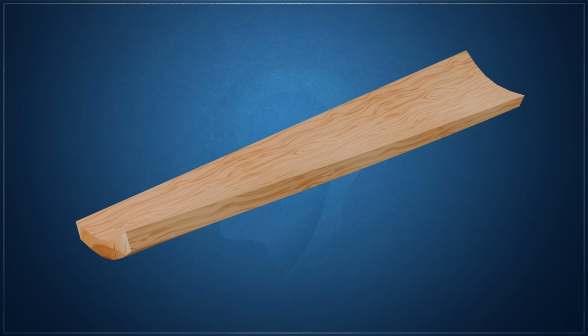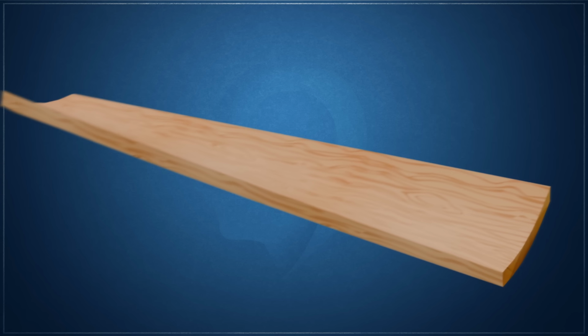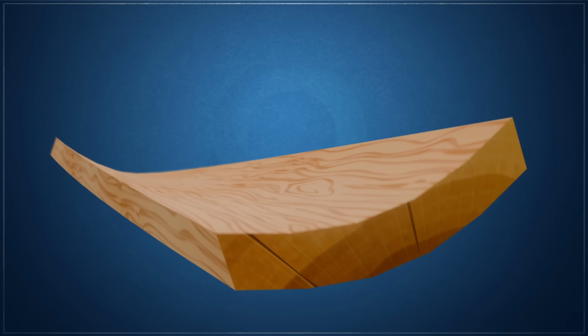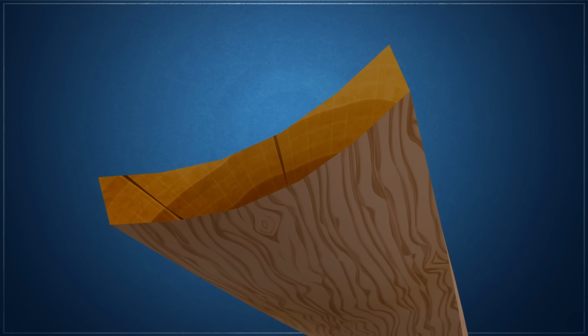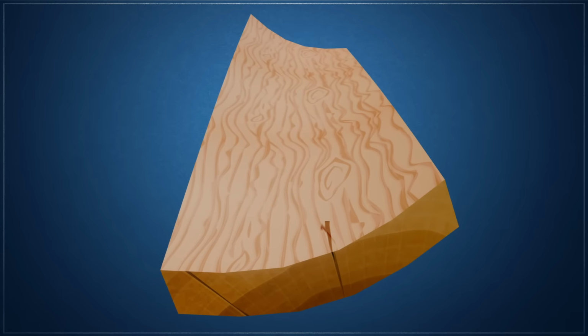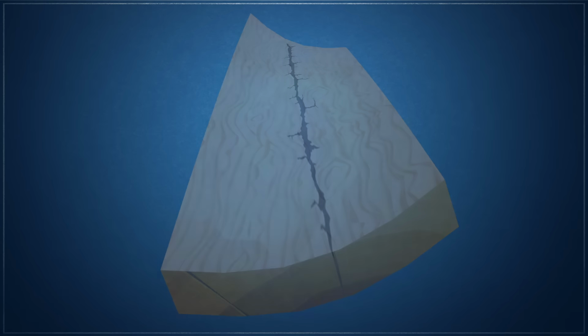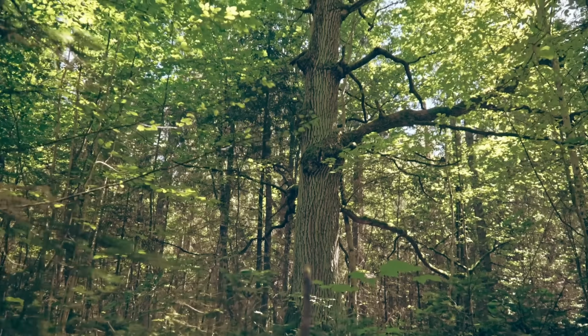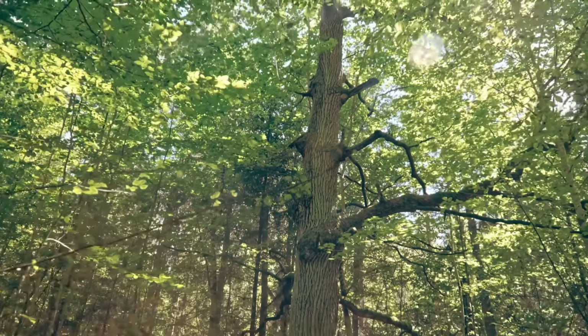As the surface moisture content drops below the fiber saturation point, the outer shell attempts to shrink, but is physically restrained by the swollen, wet interior. This creates large internal moisture gradients and nonlinear shrinkage behaviors, inducing structural stresses that lead to surface checking, splitting, and internal cracking.